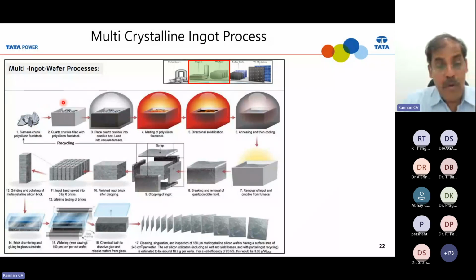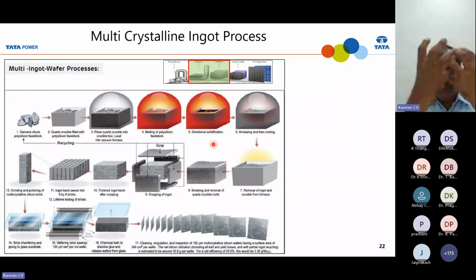And then this will be loaded into the crucible, and this crucible is a silica crucible. Then there is a susceptor to protect the crucible from deforming and damage. Then it will be loaded into the furnace, and then the furnace will get heated. The polysilicon material inside the crucible gets melted, and then after that there is a controlled cooling from the bottom. So after melting, there is a cooling from the bottom. So the bottom side has a cooling mechanism.